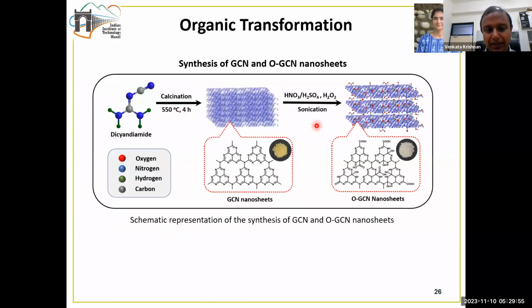And this is how we prepared this catalyst. We started from melamine, or dicyandiamide. We calcined it at 550 degrees centigrade to obtain the normal graphitic carbon nitride nanosheets. And subsequently, we did an acid treatment, wherein HNO3 along with H2SO4 was used for the functionalization, the oxidation, where an oxidizing agent, H2O2, has been utilized. So that's how we end up getting this oxidized form of graphitic carbon nitride.